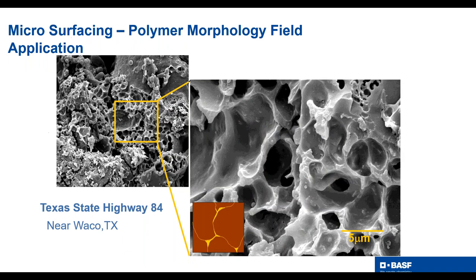What I wanted to show you next is, remember that little film around the asphalt droplets that the polymer formed, and you can see that little brown animated picture in it. This is an actual microsurfacing field sample from a highway near Waco, Texas, and Koichi Takamura, many years ago an R&D person with BASF, got this asphalt sample, and he found a way to get the asphalt out of it. And you'll notice in the top left picture there's the aggregate and you'll see the polymer attached to some of the aggregate. And you'll see these little droplets, and you can really see it in the picture to the right where it's a little bit concentrated, seeing how that polymer, just imagine the asphalt being in there.